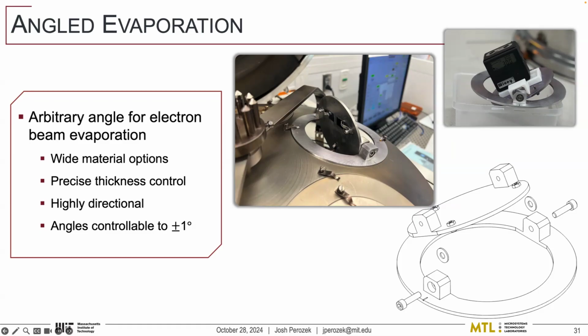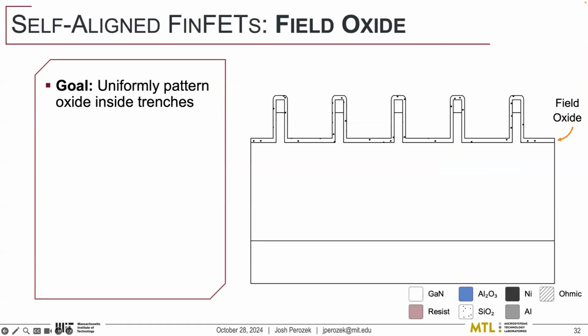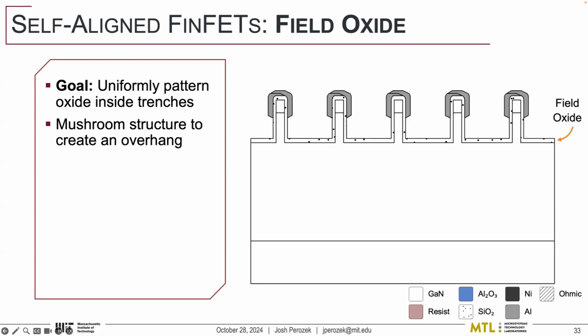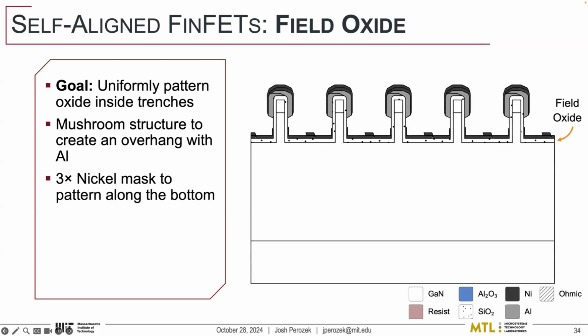The process is a little complicated, but hopefully quite interesting. So the first thing that we need to do is to have 4 regions patterned along the sidewall of these fins. The first one is a field oxide. This is a spacer between your gate and your drain that prevents the gate oxide from breaking prematurely. And the goal is to just have oxide at the very bottom of these trenches. So what we can do is form that same mushroom structure that we had before. We can use aluminum for that. And then if we come in with nickel,